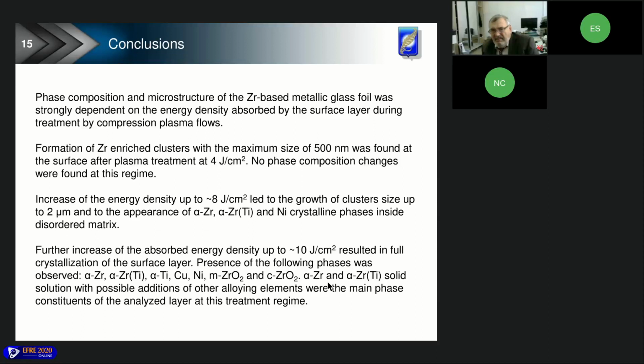The cooling rate of the plasma impact was much lower than the critical rate necessary to preserve disordered structure. Maybe at lower pulse duration the cooling rate will be higher, but in any case, surface layer melting under conditions of plasma disruption events in different kinds of plasma installations, with real duration of milliseconds or higher, will lead to crystallization of metallic glass.